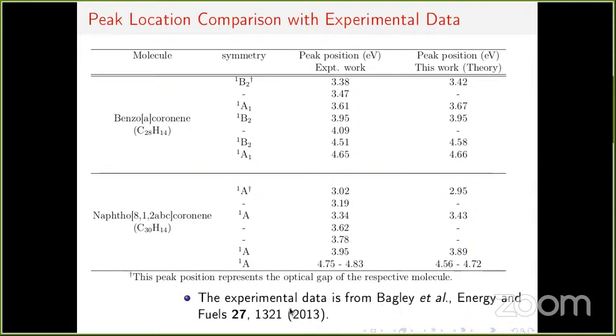So we are comparing our theoretical results with the experimental data of Bagley et al. These are the symmetries of our calculated peaks, these are the peaks which the experimentalists observed, and these are the locations of the peaks according to our theory, screened parameter calculations. You can see that generally the agreement is very good, so we were very happy with this. So this finishes my discussion of lower symmetry polyaromatic hydrocarbons.